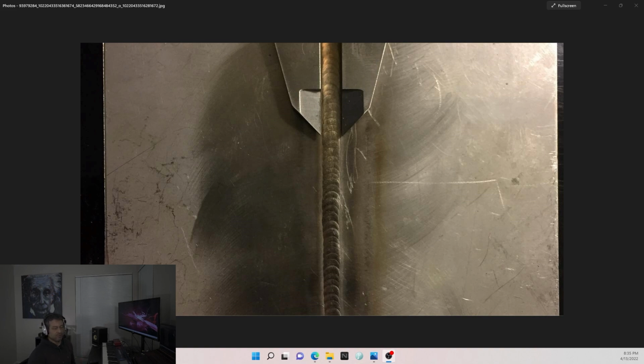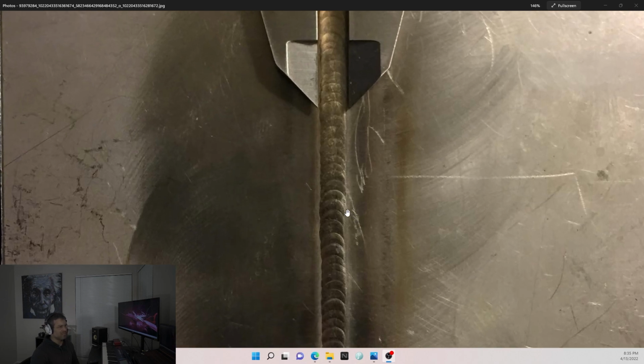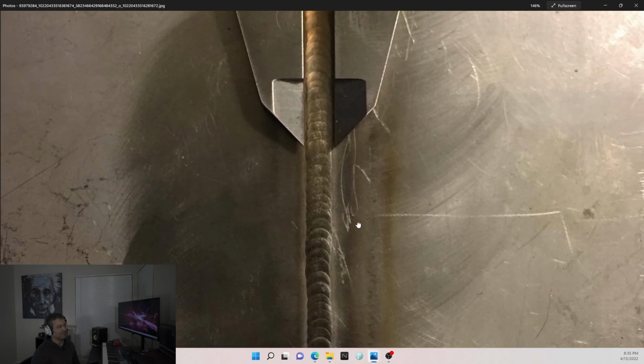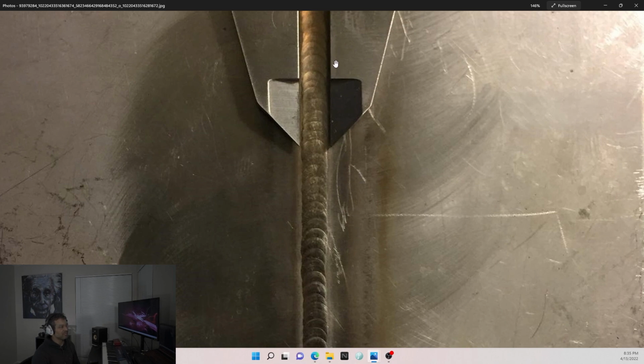Now, who cares about what my beads look like? As long as I'm getting full penetration and there's no porosity, beads don't really matter. I mean, of course, your visual inspection, but what they're looking for is consistency on the outside of your beads. So the bead width can vary. You know, your bead can be wide and it can shrink, but it cannot do it abruptly, and it can't do it too much.